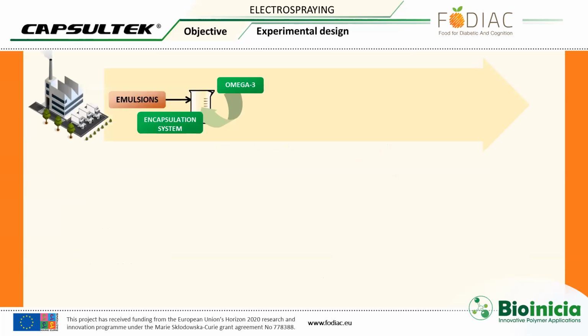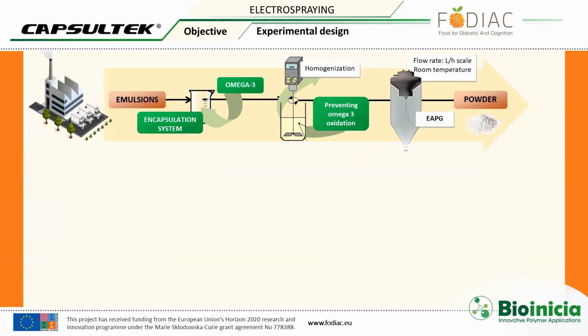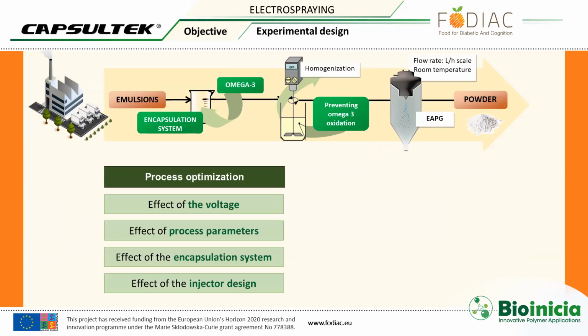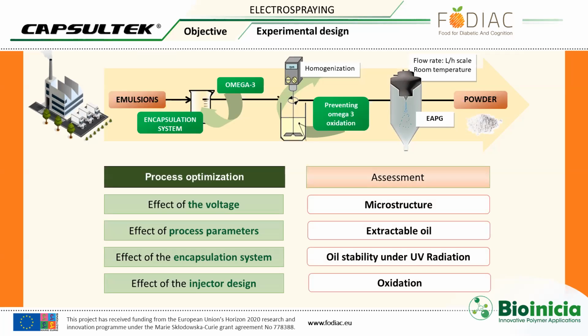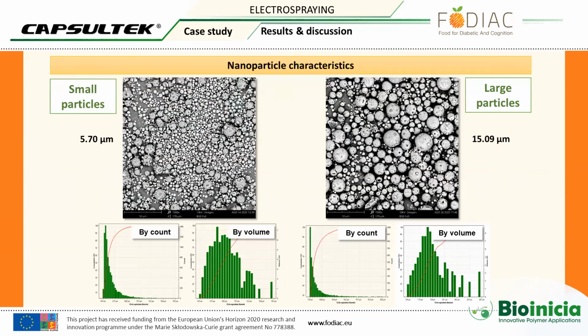We have selected omega-3 as a model compound because it is really challenging. To scale up the technology, we have performed a process optimization, taking into account the voltage, the different process parameters, the encapsulation formulation, and also the injector design. We have characterized the particles in terms of microstructure, extractable oil, oil stability, and oxidation. We have produced two optimized systems with different particle sizes: one smaller, with a medium particle size of 5 microns, and another with large particles, with a medium particle size of 15 microns.